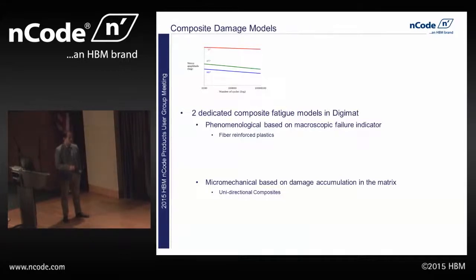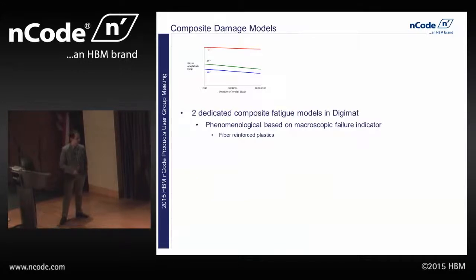And the big difference here is that if you look at a small point in a unidirectional composite, you have fibers running through that point of the material, and generally your fatigue damage is happening inside of that matrix material. So this model is really formulated on the matrix, whereas this model is really focused more at the composite level. So since the topic of conversation today is around fiber-reinforced plastics, we'll look at this phenomenological model and talk a little bit more about what it is.